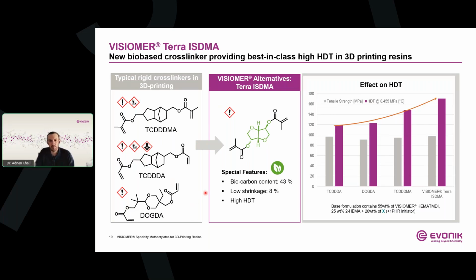And when we applied the Terra ISDMA in the same model formulation, we observed the highest HDT value of all the materials that were investigated, while also maintaining the tensile strength at a comparable level. So at the same time, the ISDMA offers a low shrinkage and a significant renewable carbon content, making it, again, an attractive solution for high performance 3D printing resins.